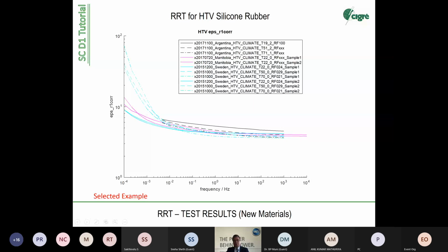Here, very promising at 50 Hertz, very small scatter, also with the air reference method. And in the low frequency range, you see a little bit higher scatter. But tendency is very clear here, with lower scatter than with the LSR. Why? We think, or we concluded that the interfaces give a clear signal, give a clear process behind the response, and that when this happens, then you really measure something that is really going on. So it's not determined by scatter, it's more determined by a real physical process.